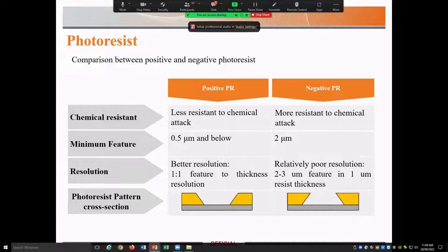Not necessarily, I would say. You need to choose the right type of photoresist with the right viscosity, and of course the polarity of it, and also the spinning speed. For example, there are different types of negative photoresist with different viscosities. If you go for very low spinning speed with high viscosity resist, you may not get a very flat surface, and you will get edge bead, which is quite hard to work around, and you won't get a very good uniformity in your film thickness. So it's about choosing the right type of photoresist.